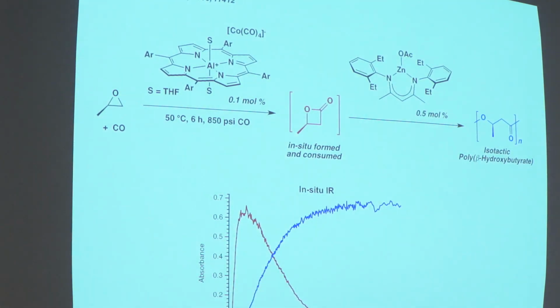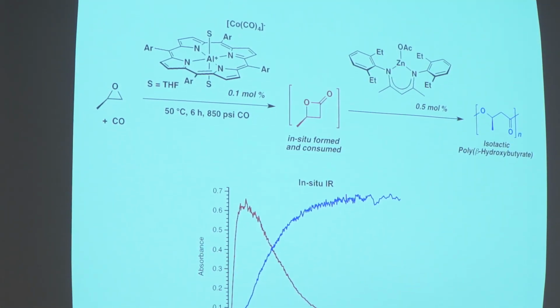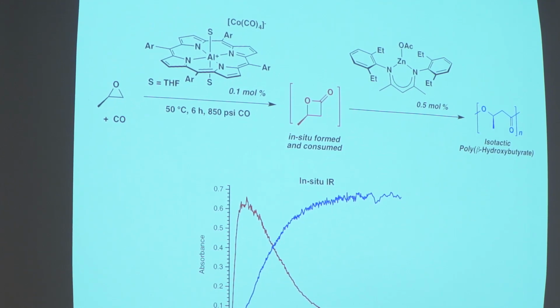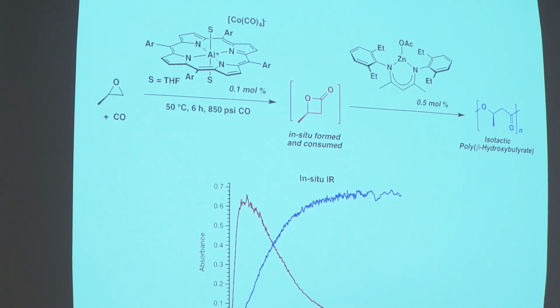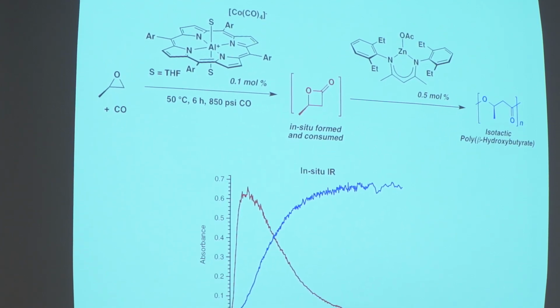Jacobsen has a beautiful way to do the hydrolysis of it enantioselectively, but you're actually burning half of the epoxide to make propylene glycol, and so immediately this would at best be twice as expensive as propylene oxide. So again, we can make this polymer from this lactone, from this epoxide, and the best way to do that now is you do a kinetic resolution where you would basically eat this up with water and make glycol, and then you would have optically active epoxide.